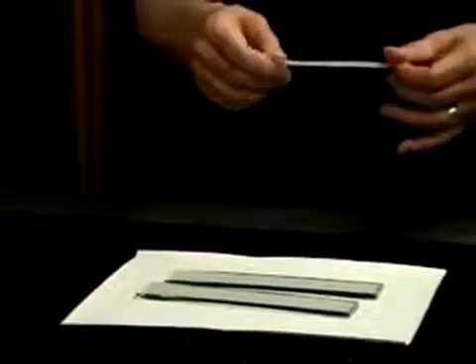To form the wedge, the lab specifies that a wedge be formed with a piece of material of known thickness. If the thickness gets much more than 70-80 microns, the wedge angle will be so wide that the fringes will be very closely spaced and too difficult to see and count. So what's turned out to be very handy is a piece of trash bag. The cheaper varieties of trash bags from the local supermarket are on the order of 25-30 microns thickness, which is just about what you need. They're also stamped with the thickness so that becomes your known value.